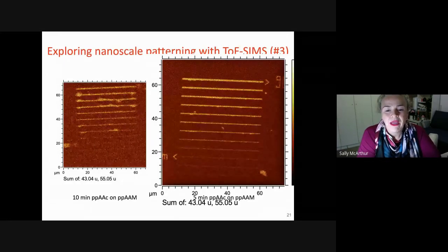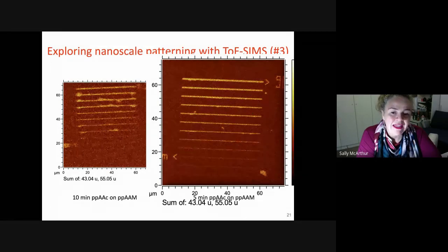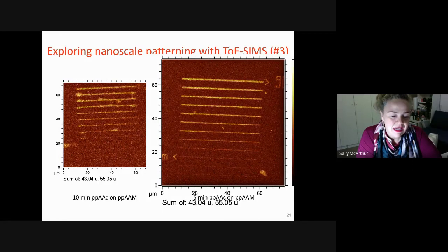So what we have done is gone in and done some multivariate analysis as well of the images. The challenge you've got with imaging is the way this data is collected to get high spatial resolution means that we have poor mass resolution. The data that we use to do multivariate analysis needs to have high mass resolution. And so we haven't been able to produce much more out of the multivariate analysis than we get out of this sort of univariate analysis of looking at just specific peaks and summing them together to get more intensity. But yeah.